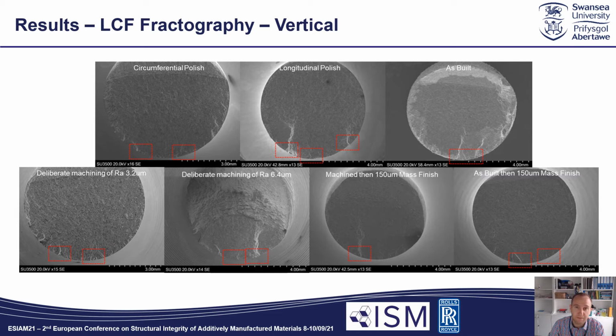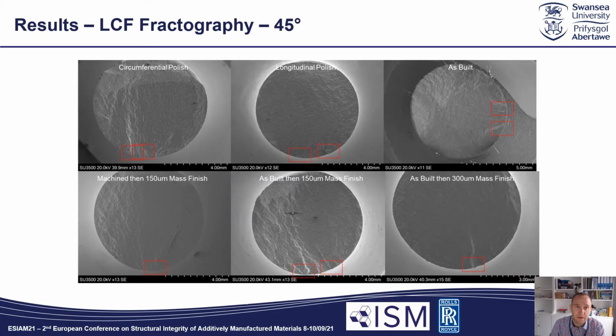crack growth behavior. We can make out the initiation sites though, as highlighted by the red boxes, and in each case, nucleation appears to have started near or at the surface, which of course is a good indication that the material is fully consolidated with minimal evidence of failure originating from any subsurface anomalies. And it's also a similar case for the 45s, where there's minimal difference or anything of note across the different fracture surfaces as given here.